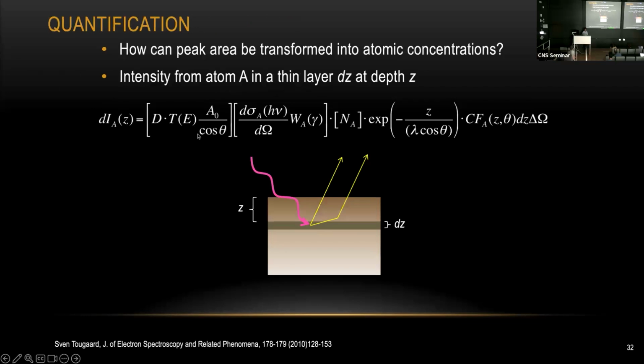And here is just a very brief summary of the formula for how we do the quantification. The formula is based on the assumption in the cartoon right here. So we're assuming the signal coming out from your surface is about z distance from the surface, and the region we're going to detect is about dz. The first term here depends on your electron energy analyzer, and the next two terms depend on the photo excitation. The exponential term depends on the inelastic electron scattering, and the very last term depends on the elastic electron scattering. So by plugging in all the numbers we get from the machine, we will be able to generate all the quantification information for your sample.